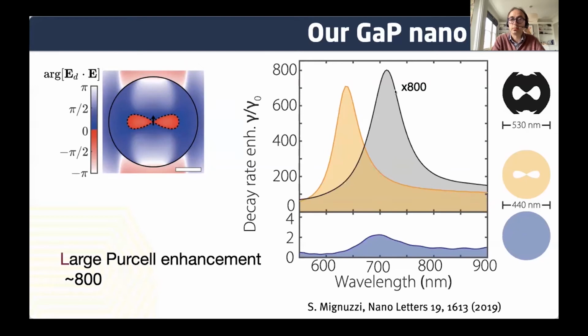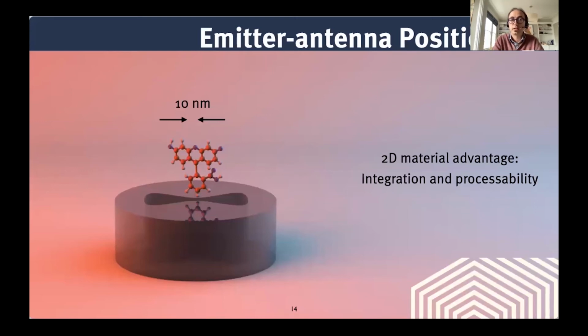But what I want to say is that to achieve this black curve here in the middle of the plot, which has a resonance around 700 nanometer, we need to use the black antenna that you see on the top right, which has a very strange shape. And in particular, has a very small gap in the middle. So this small gap is around 10 nanometer in size. And this is one of the key challenges in nanophotonics.